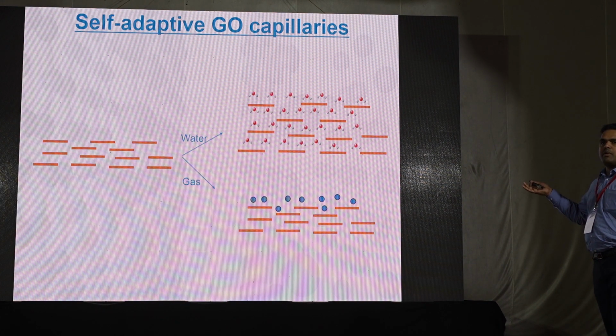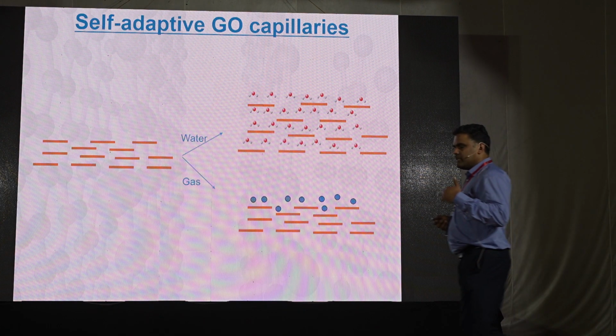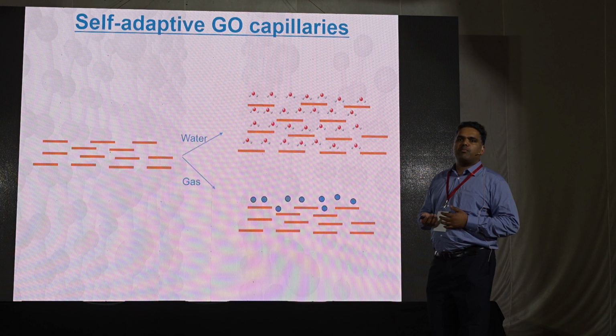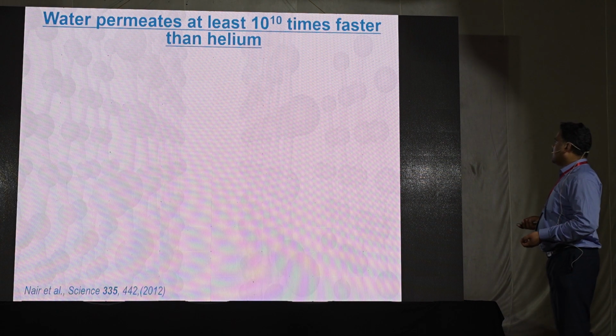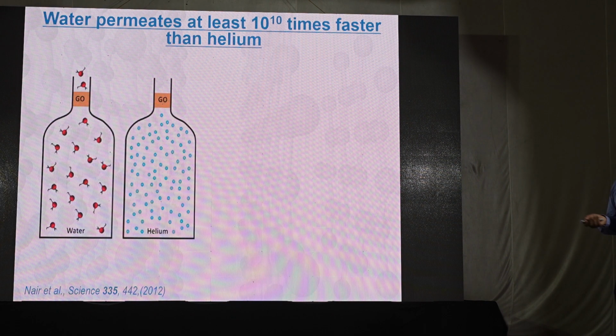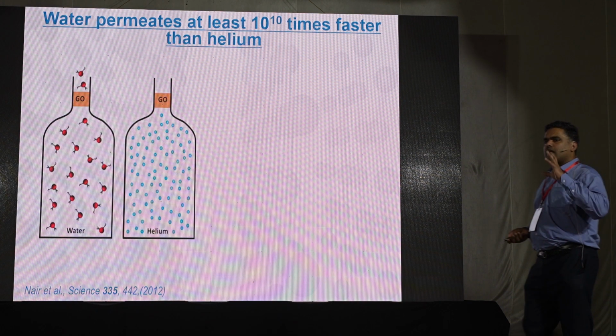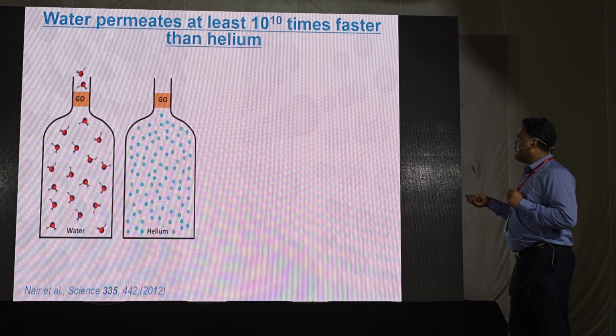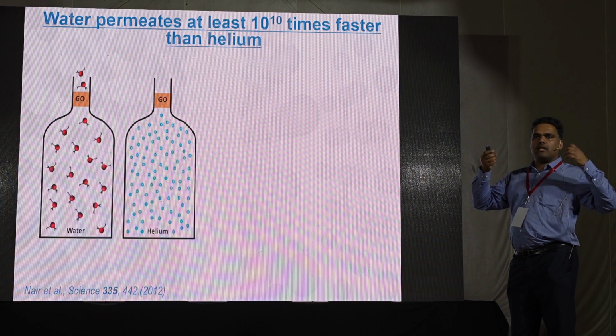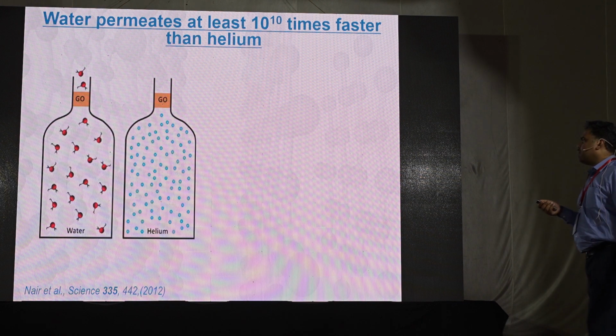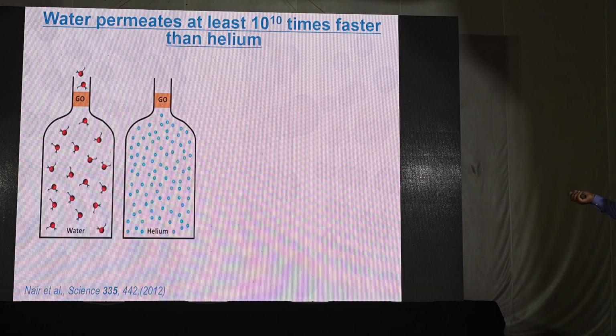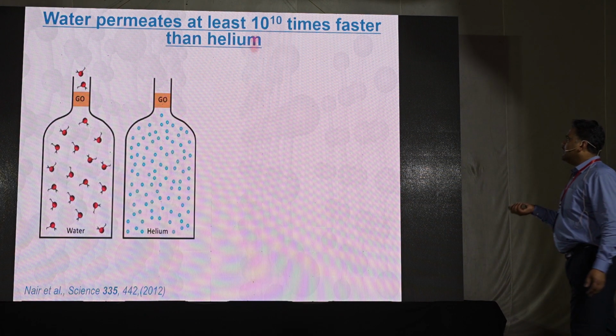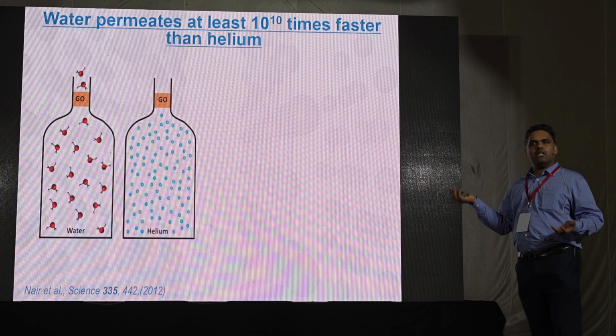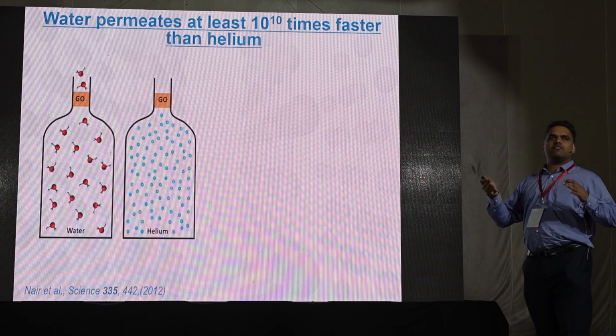So this type of membrane is really a gas barrier membrane, but it allows water, which makes it an ideal membrane for water filtration and different kinds of technologies. So what we found is that, compared to all other different materials, graphene oxide is something very unique. If you take a graphene oxide membrane, it's basically a sheet of paper, exactly similar to A4 size printing paper. It looks brown in color. You take two bottles, one bottle with helium gas and another bottle with water, and you seal both bottles with the graphene oxide, and you will see that helium cannot go through the membrane, but water can easily go through. Easily means water goes through as if the membrane were not there.